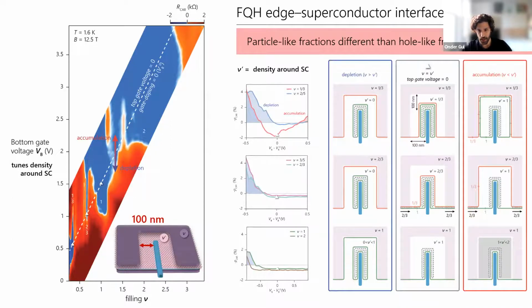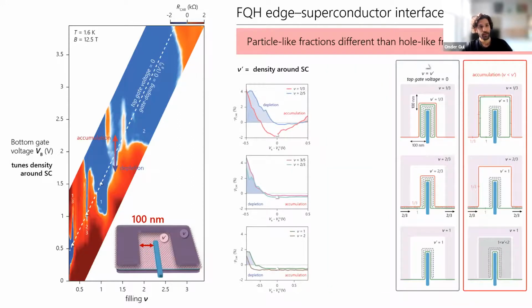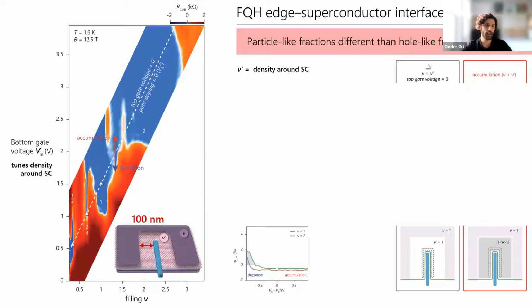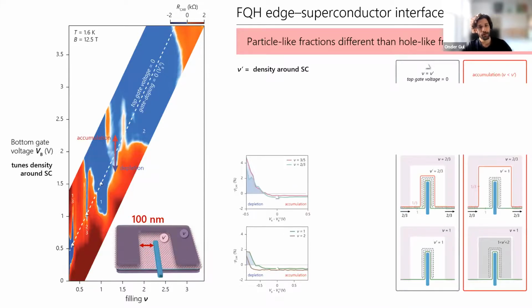The lowest integer edge mode corresponding to filling 1 is shown in green, and the 1/3 edge mode is shown in orange. It is straightforward to see that depletion by gates should suppress the signal. Basically, the edge mode doesn't efficiently see the superconductor, and the signal will be suppressed. So I will not focus on that case. I will just blank it. So let's first look at the case of bulk filling 1. Here, the incoming charges are carried by the integer edge. For the case of 2/3 bulk filling, again, the incoming charges are carried by an integer edge, similar to the case of bulk filling 1.